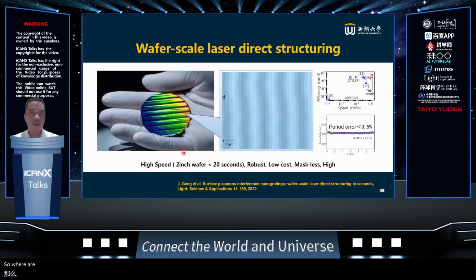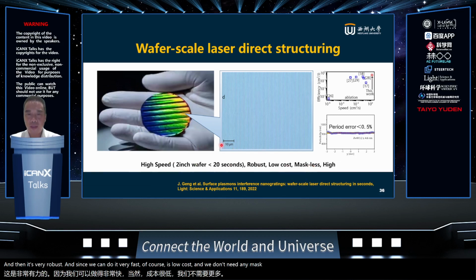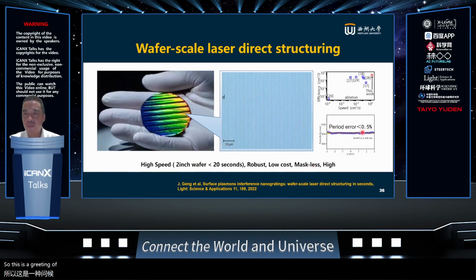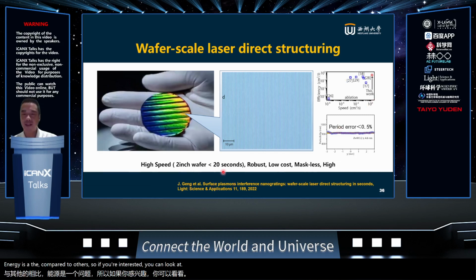So very high speed, because this is a 2-inch wafer, and we write the whole 2-inch wafer within 20 seconds. And it's very robust. And since we can do it very fast, of course, it's low cost. And we don't need any mask. So this is a grating with period error below 0.5 for the whole 2-inch wafer. And it's also extremely energy efficient. We can achieve very high speed, but with extremely low energy as compared to others. So if you're interested, you can look at details from this paper.